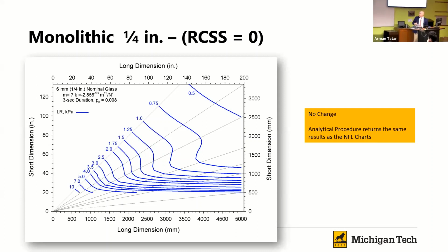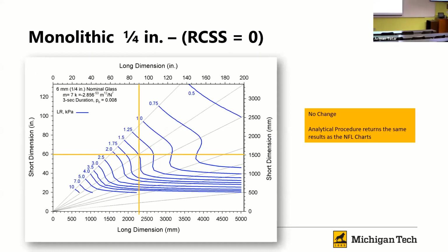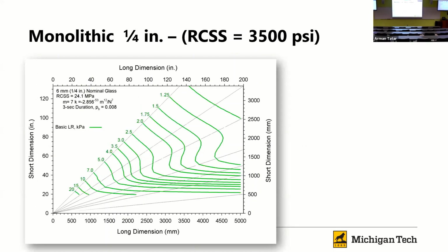So for monolithic annealed glass, there is no change because this is exactly what the charts that were in the standard were, and so there's not a difference there. So this is the same chart that we had before. Now, if I want to go to heat strengthened glass, then the process there would have been we took the non-factored load chart and we multiplied by 2. So we'll see that all these numbers increased by a factor of 2, and I just redrew the chart, or really I just adjusted the numbers.